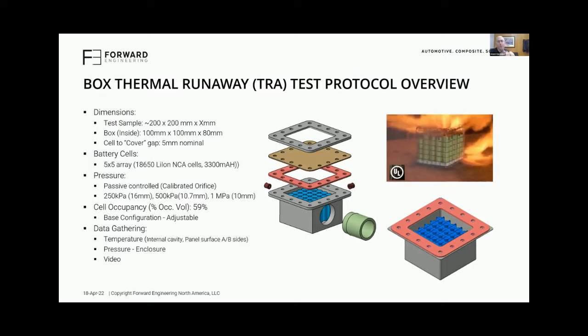And what we're doing is using resistive heaters, and I'll show you some detailed images. We're using resistive heaters to gradually and gently bring the temperature of those cells up to approaching the point at which they go into thermal runaway on their own. And that's part of the magic, is to gradually and smoothly initiate thermal runaway. And then once that thermal runaway begins, all 25 cells go into thermal runaway. And again, back to the point of it being temperature, ablative forces, and pressure.